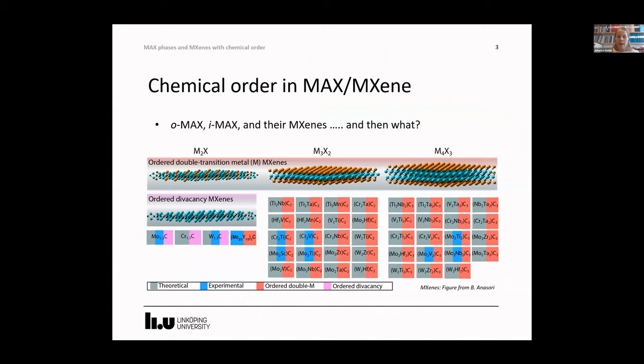But let's start by looking at the map of where we are today. I'm sure that many of you are familiar with this image, showing that in addition to traditional MXenes, we have chemically ordered MXenes. For the 2-1-1s, we have in-plane chemical ordering in the M layers. And for the 3-1-2 and 4-1-3, we have out-of-plane ordering with alternating M layers. In this image, gray represents the MXenes that have been predicted or investigated theoretically, and blue represents those that have been found experimentally. And as you can see, quite many remain to be discovered.